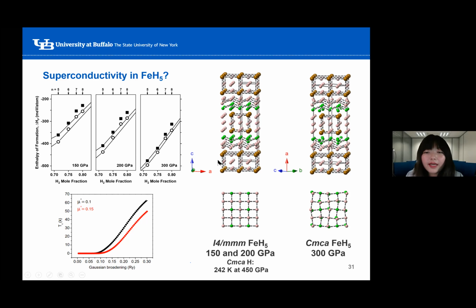So first, let's look at whether there's any superconductivity in the FeH5 structure. From our search, we identified the known I4/mmm FeH5 phase at 150 and 200 GPa. And at 300 GPa, we found a new structure, Cmca, that's structurally related to the I4/mmm phase. In both of the structures, they are comprised of simple cubic-like FeH3 blocks.